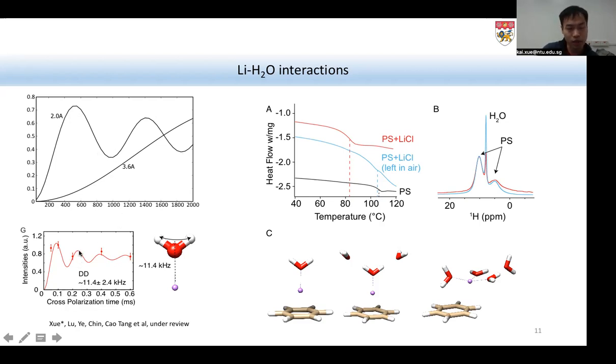So what I measured in this three-component system is a dipolar coupling of approximately 11.4 kilohertz, which corresponds to approximately 1.6 angstroms. But I will probably not interpret it into a distance here, because the system is complicated. We probably have more than one spin inside, and water in the system definitely undergoes certain motions, so what I measured is actually an average interaction. But what can be said here is that since this dipolar coupling is so large, it definitely matches more with the interaction driven by charge affinity.